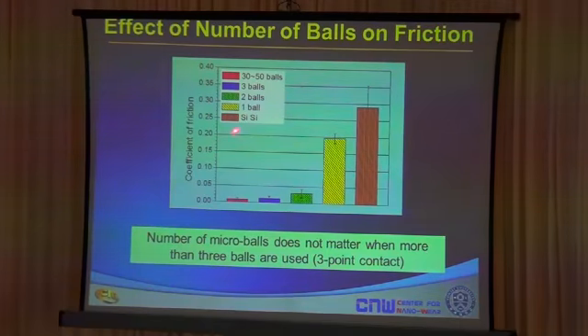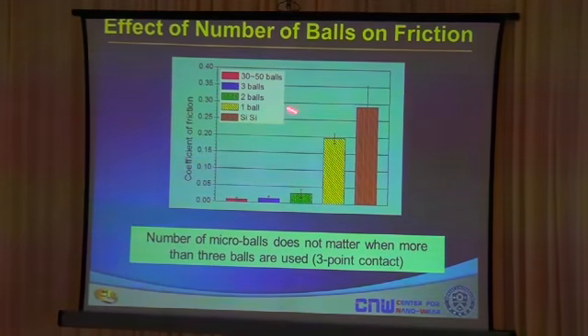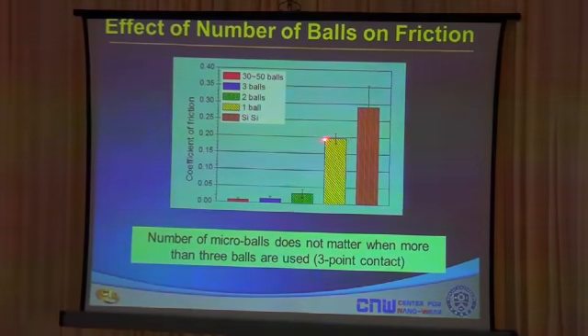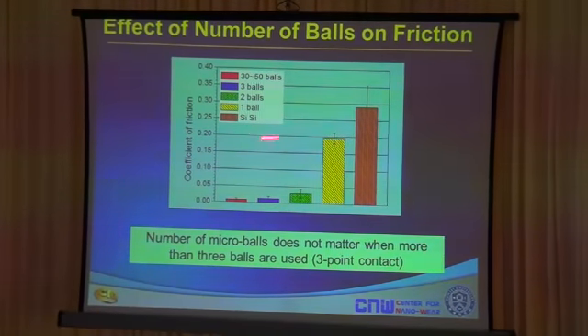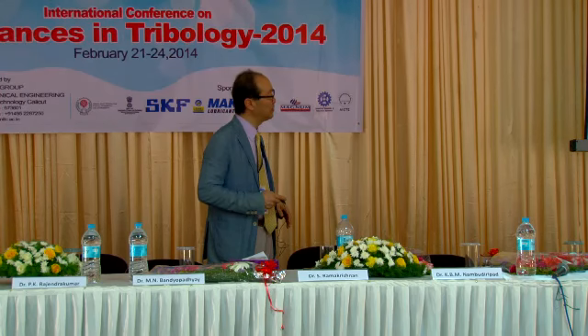Now, we also studied the effect of number of ball bearings. This would be without ball bearings, the red one, the orange one. With one ball at the interface, you can see that the friction coefficient can be reduced, but it's still high at about 0.2. With two balls, it goes down significantly. With three balls, it goes down further. With about 30 balls at the interface, you don't have too much decrease. So the number of balls actually is not a critical factor as long as you have 3 or more, because you would need 3 contacting points to support 2 plates.